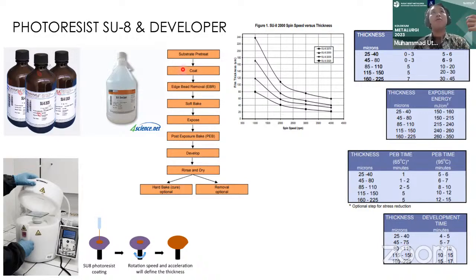And the way we use these chemicals is at first we coat this SU8 on top of the silicon wafer using this kind of spin coater. So we put the silicon wafer on top of this spin coater, and then we put SU8 on top of the silicon wafer, and then we spin the silicon wafer to get an even thickness of SU8 film. And then we will do what we call a soft baking, or basically heating up the silicon wafer to get the SU8 to stick to the silicon wafer. And before I continue about the soft baking process, we usually have a lot of SU8 products, and they are defined by how the film thickness relates to the spinning speed during the spin coating.